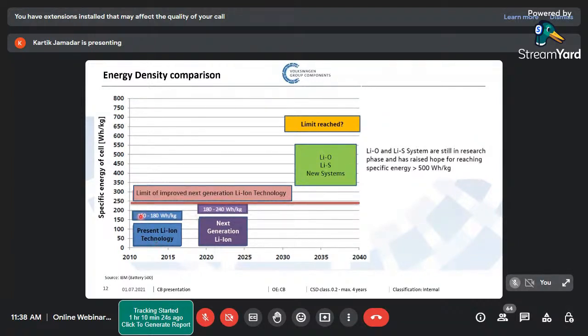Initially, till 2015, we were working with basically 180 watt hour per kilogram, where we were using mainly 33% nickel, 33% cobalt, 33% manganese. It was quite a good cell, a compromise from all three metal oxides. Nickel was giving high capacity, cobalt was giving high voltage efficiency. It means even at around 4.3 volt, nickel would not release oxygen. Cobalt was suppressing nickel from releasing oxygen. And manganese was giving high thermal property. It means even at high temperature, nickel was not releasing oxygen.